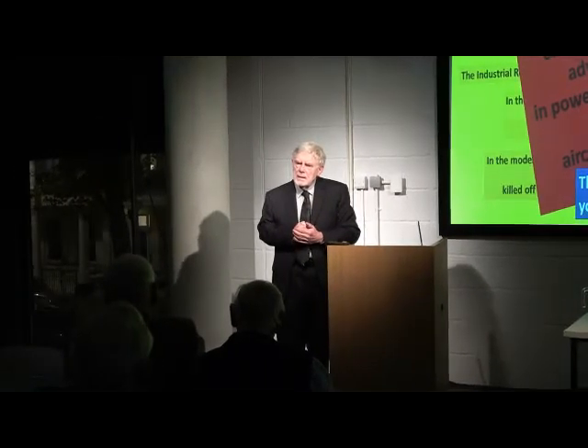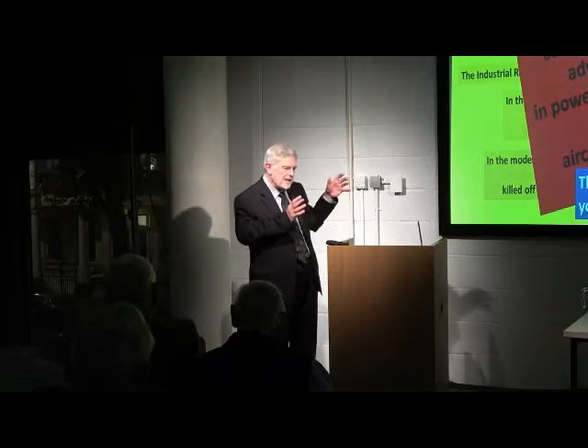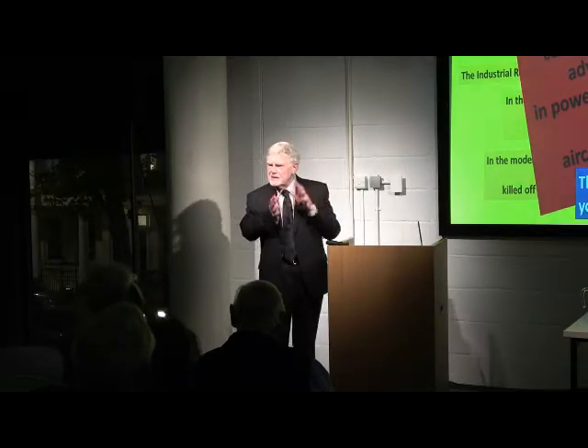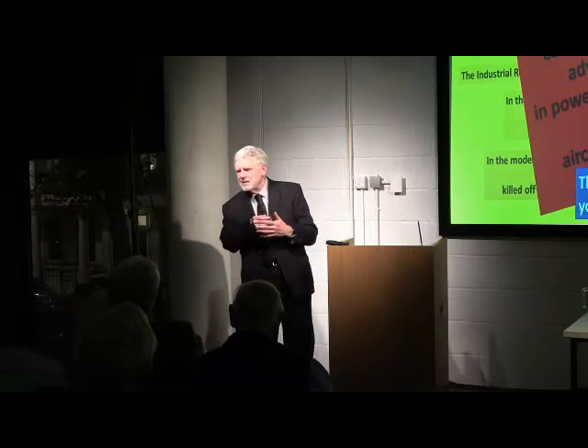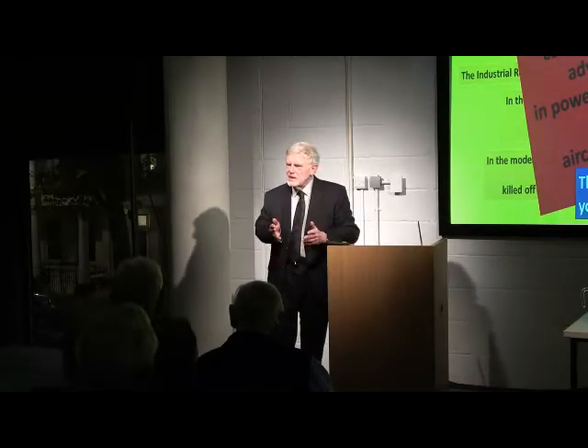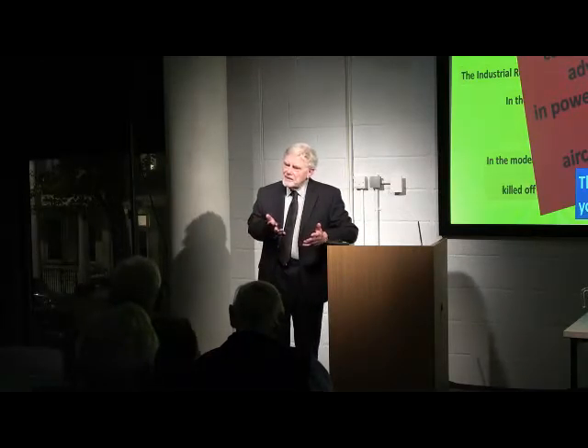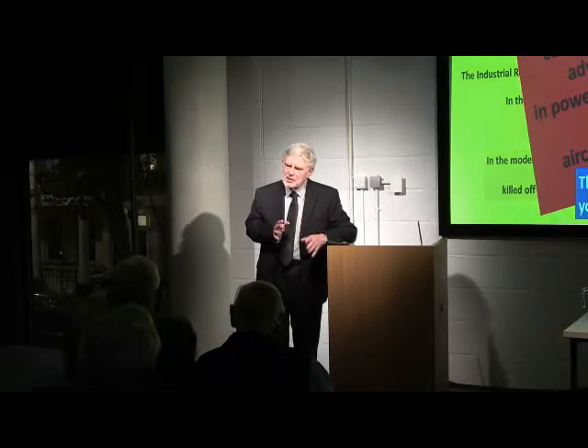Yeah. Someone mentioned titanium, and you've mentioned it being a high temperature material, but it breaks down with oxygen, as I understand. Oxygen breaks it down somehow. Basically, what's happening, Charles, is that the oxygen diffuses into the material and then embrittles it. It stops things called dislocations in the material moving around very easily. The oxygen is also another problem in the manufacture of the material. You have to produce the material under very, very high vacuum conditions. If there was any oxygen around at all, that material was going to be absolutely useless.